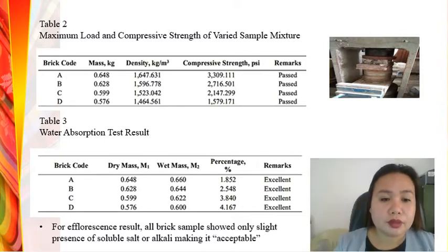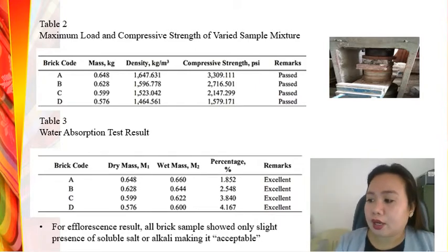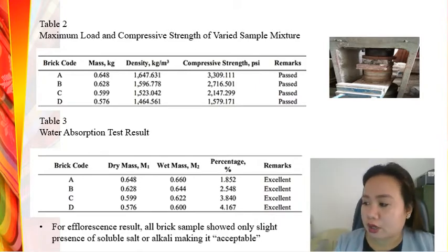In terms of water absorption, a concrete brick can absorb or discharge moisture content because of its dryness and porosity. The brick will absorb water if it is dry, thus making it poor, and the mortar will fail. It reduces the general strength of the structure. With this, a water absorption test as per IS 3495 was performed. It is noted that the specimens were dried and cooled down at room temperature before the individual dry mass was recorded using the digital weighing scale.